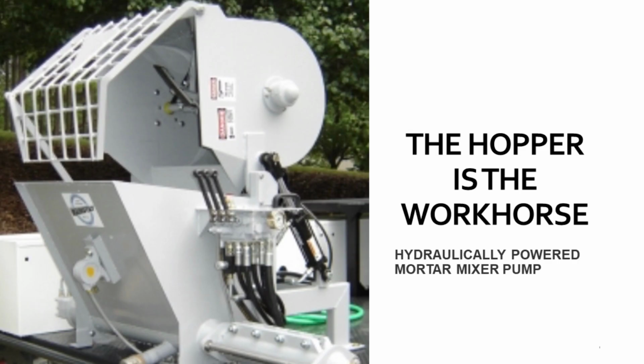We custom build them. They've got the mortar mixer on the back, which is the workhorse of everything. You can put about 8 bags of mortar in there, though most people put 5 to 6 at a time. Mix it up, dump it, and they start pumping it out the rotor stator here. This unit will do about 200 feet, so you'll have to turn around on a 400-foot section, or you can use something like a Putzmeister piston pump. We use those as well sometimes.